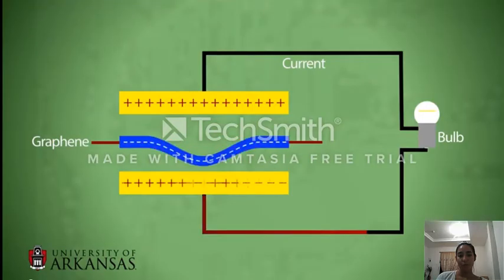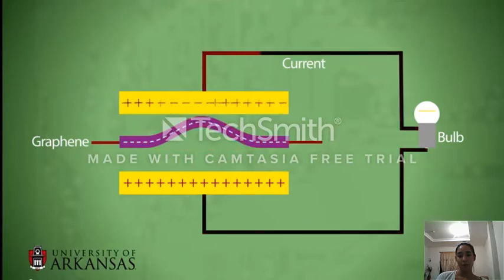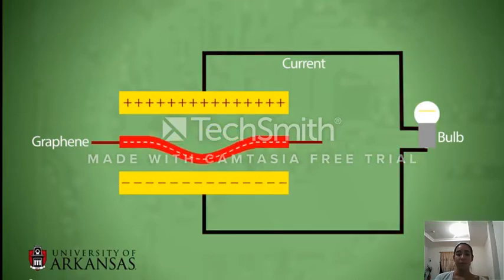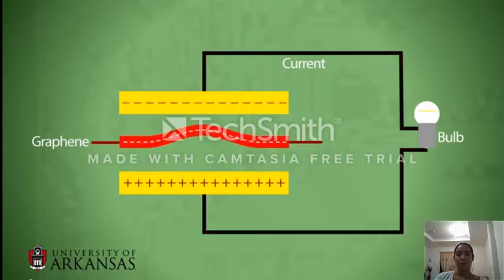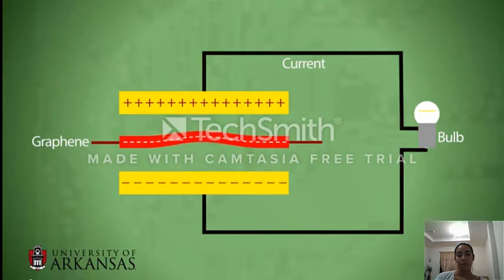If we place a charge on that ripple and it moves suddenly near a grounded conducting electrode, charge will flow in that conducting electrode basically to screen the charge that's moving toward it. If we had another electrode above it, when it flipped back, then the charge would flow, say in a circuit, up to this thing here. And the size of the samples that we look at are 10 microns by 10 microns, which is pretty small because about 20,000 of those could fit on the head of a pin. But one of these 10 micron by 10 micron areas could produce 10 microwatts of power continuously.